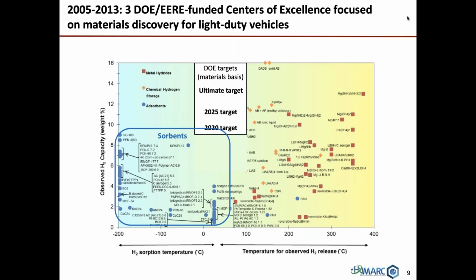So you see that the highest capacities in this block here are materials that are stored at like liquid nitrogen temperature. And what that is caused by is that the hydrogen interaction with these pore surfaces is very weak, maximum of about 10 kilojoules per mole. So the only way that you can get a lot of hydrogen to stay on there is to cool the material. Alternatively, the other big class of storage materials are metal hydrides.